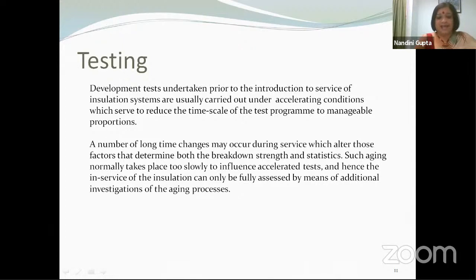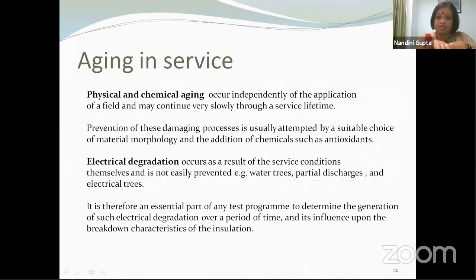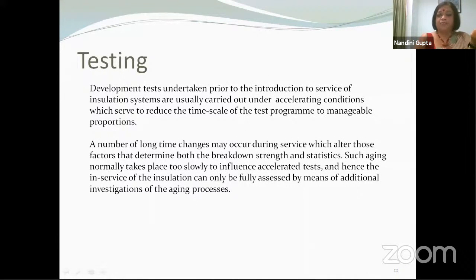A second thing is that, as I said, aging is a dynamic mechanism. So even if you perform tests under accelerated conditions, it may be such that in reality, in practice, there might be a number of long-time changes which can occur during service. Operating conditions themselves may change. The material stresses may dynamically change, which may not be possible to simulate even under aging tests. And therefore, such aging parameters will remain outside the realm of the aging test, and we have to be aware that whatever aging test we perform may not give us the complete information.